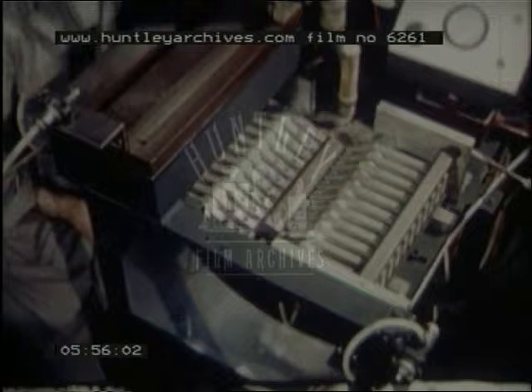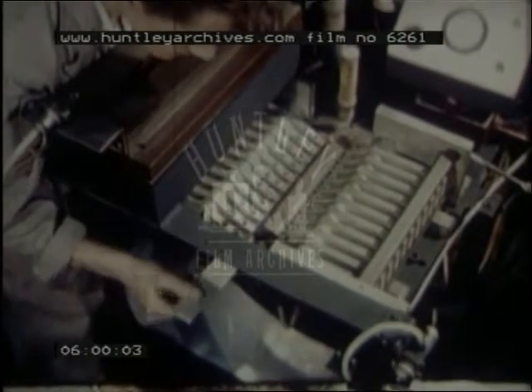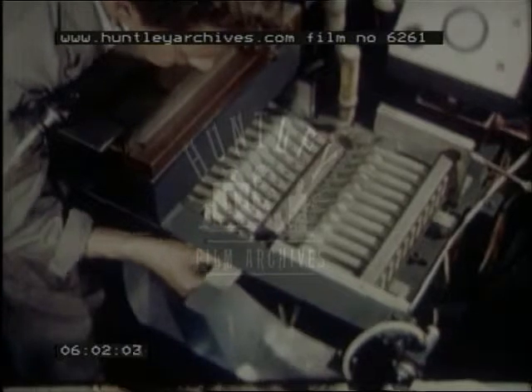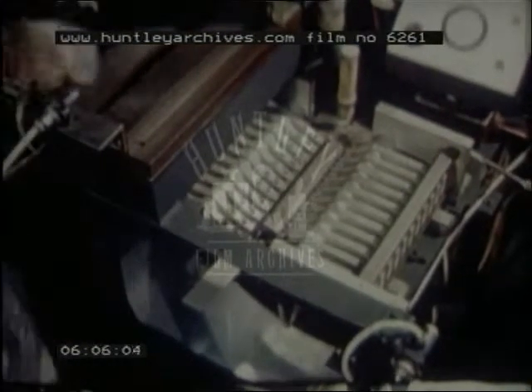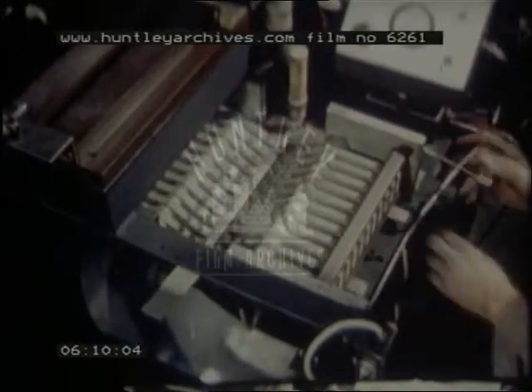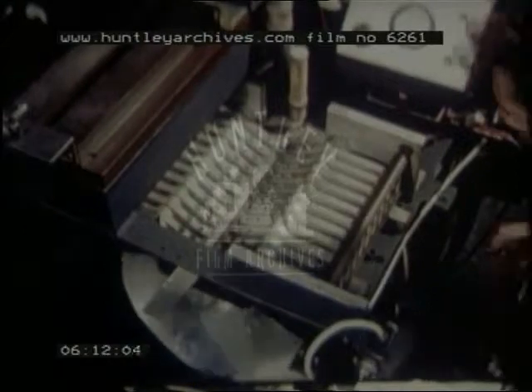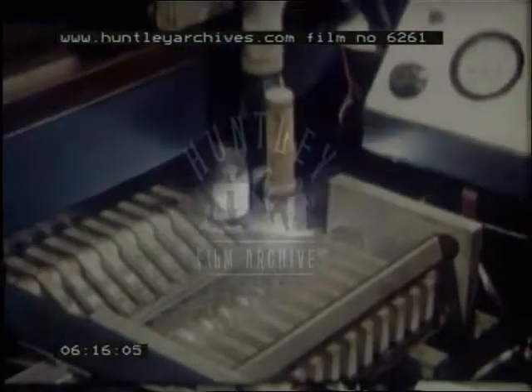The wrapper of the tub is formed by automatic arc welding, a technique which can be applied to very thin material, in this case 0.022 inches, and produces a neat, smooth weld which need not be ground or polished. Assistance on the design of the jigging arrangement was received from the aircraft industry, but the actual manufacture was carried out entirely in the customer's own workshop.